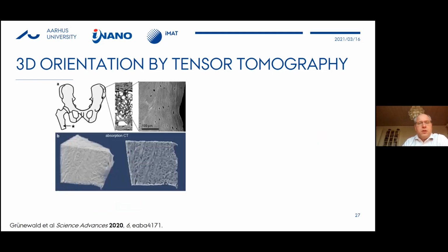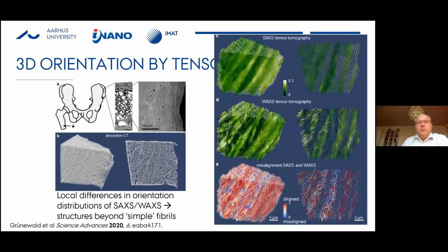And so the results come here. So here's just again the scenario. We're looking at this lamellar bone cube. And then we reconstructed the orientation of the collagen fibrils in the top. And you can see these as these little bars, and the orientation of them shows you how they are oriented. And then we did the same for the crystals within the bone. That's shown in the center plot.